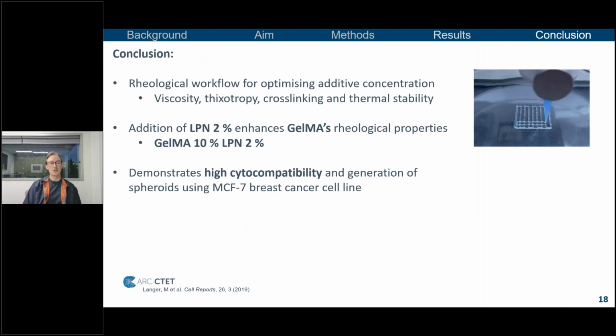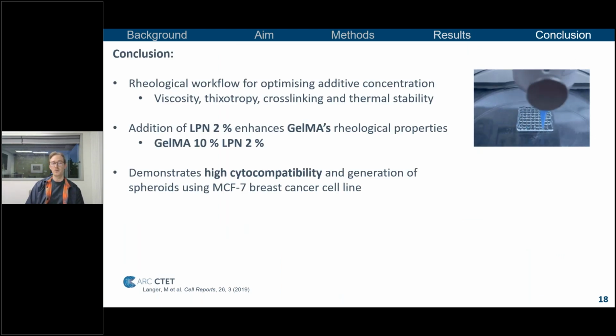In conclusion, what we're able to show here is that using a rheological workflow, we have an optimizing strategy to optimize your additive concentration using these 4 key tests: viscosity for shear thinning capability, thixotropy for your shape retention and viscoelasticity, cross-linking kinetics, and thermal stability to determine the printing window for temperature. The addition of LPN 2% enhances GelMA's rheological properties, with 10% GelMA and 2% LPN being the optimal concentration, and we demonstrated this high cytocompatibility.